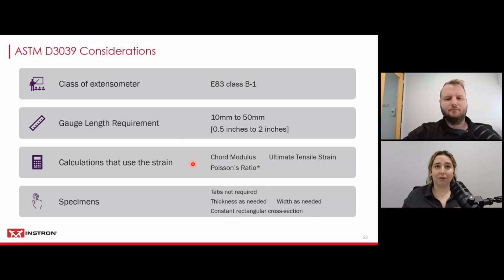Calculations that care about the strain are your chord modulus or your modulus of elasticity, your ultimate tensile strain, and then Poisson's ratio. And we only did axial testing with our extensometers, so we're not actually going to report out today on any kind of Poisson's ratio. And then lastly, just some highlights for what kind of specimens you can use in D3039. Tabs are not required. The thickness is as needed, the width is as needed, and really you just need constant rectangular cross-section.